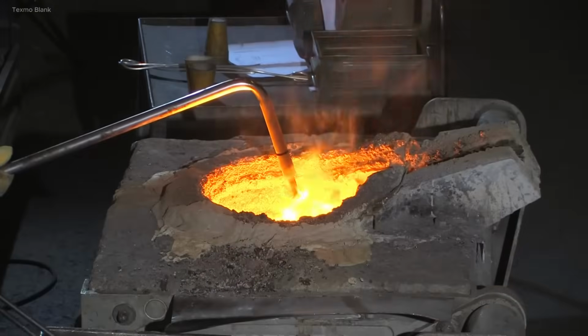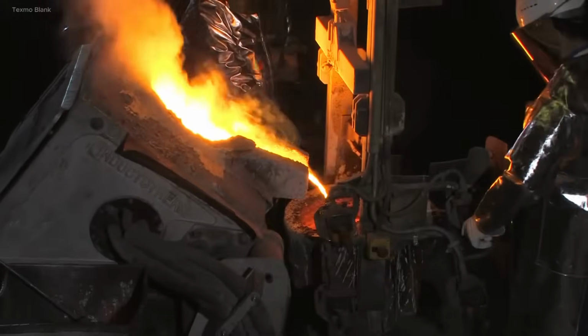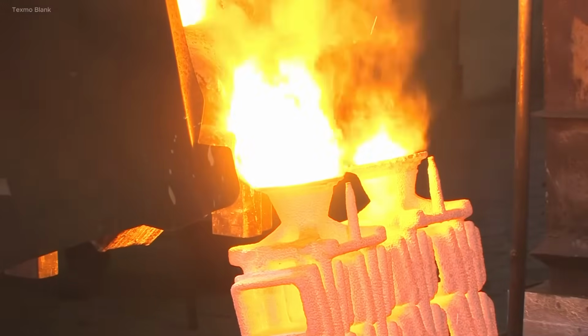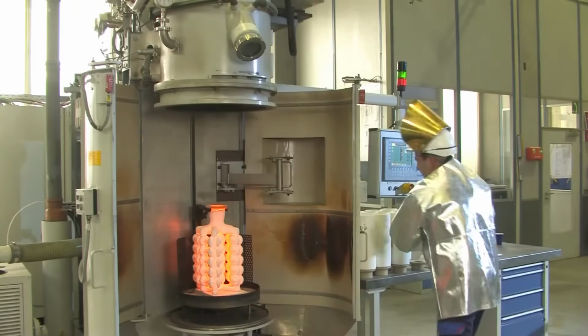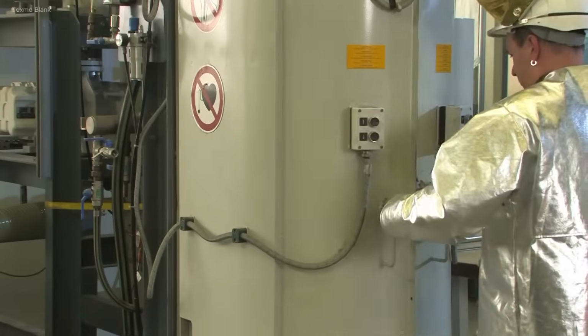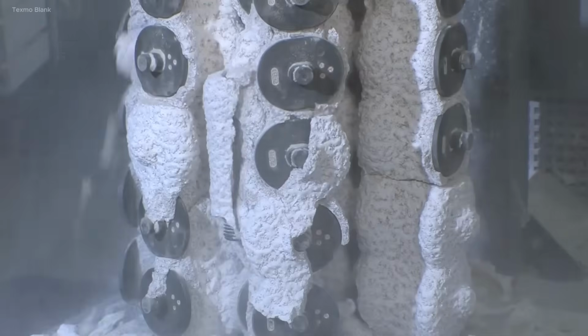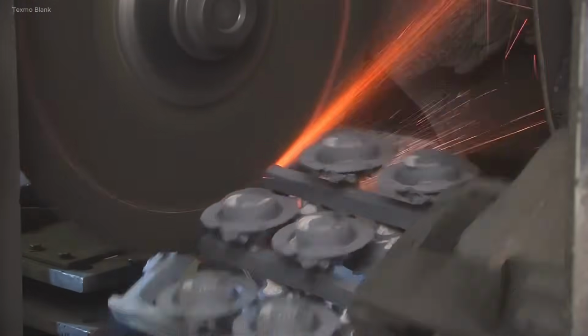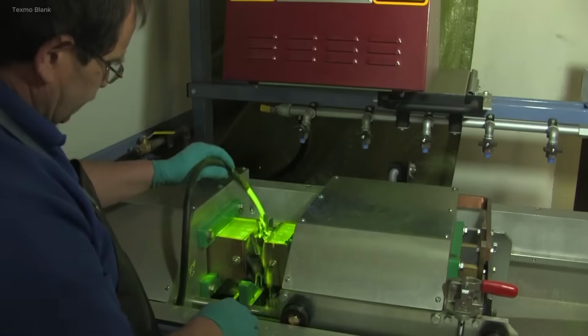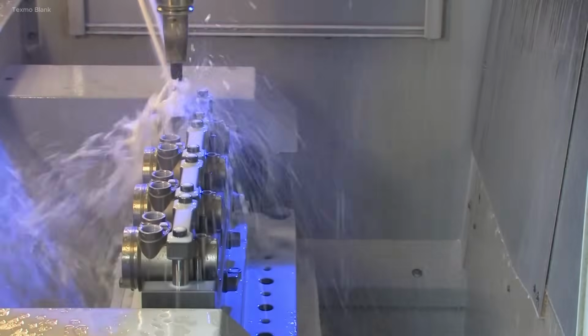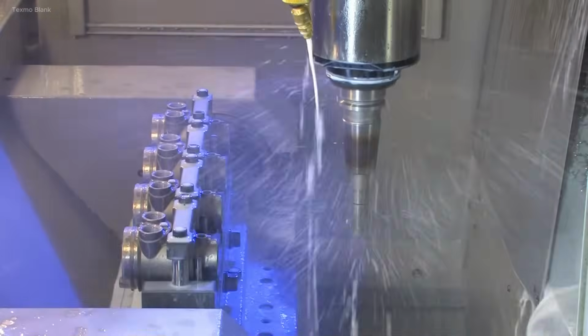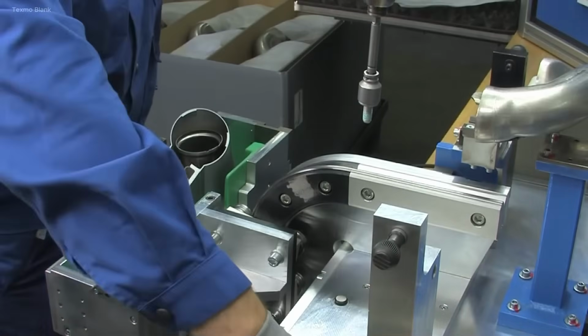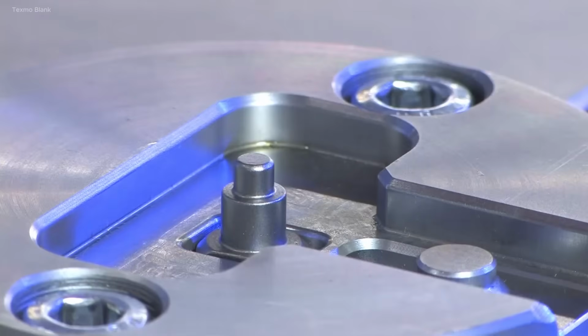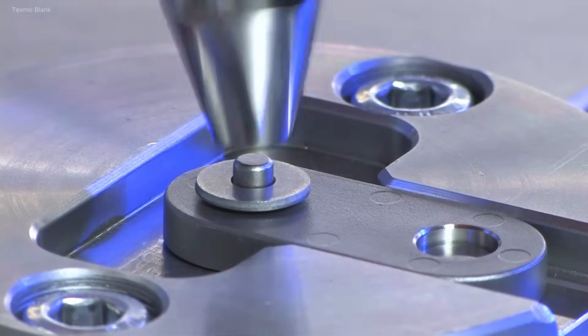Key quality factors include melt analysis, casting temperature, and shell temperature. Molten metal, up to 1,680 degrees Celsius, is poured into the shell. After cooling, the shell is removed, and the parts are separated, blasted, fettled, and possibly heat-treated. The raw part is then ready or further processed. Casting's precision complements forging, where brute force shapes metal.